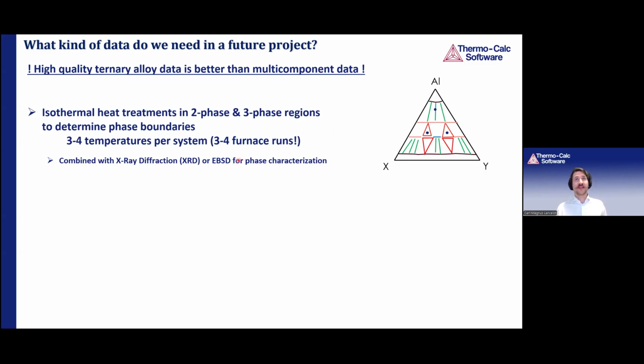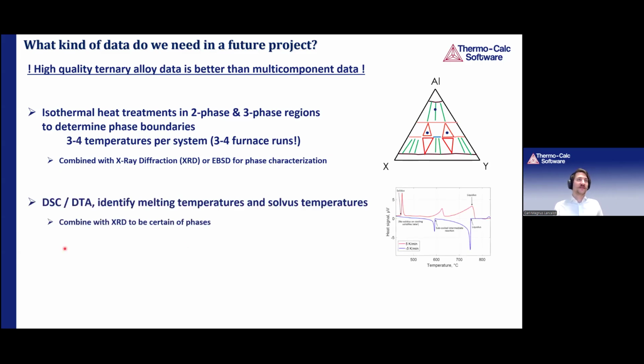Combine it with some XRD and maybe EBSD, that will help phase characterization a lot. And also DSC or even cheaper DTA analysis, differential thermal analysis, is used to identify phase transformation temperatures. So here we can scan the liquidus projection of a ternary system, so we can get the liquidus and the solidus, and also some solid phase transformation temperatures. We can combine it with XRD if we want to really be certain of the phase characterization there. And maybe a bit more expensive method, but also very useful, calorimetry. We can measure heat capacity and enthalpy of formation if we find some new ternary compounds. This will generate very important data for the assessments.